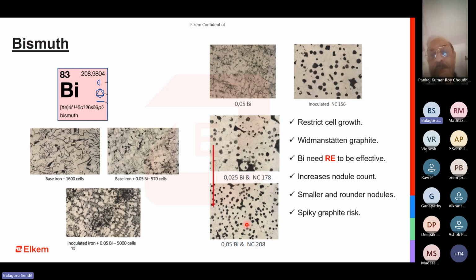The risk of what it does is that when you do not have rare earth to counter this bismuth or take advantage of the bismuth that is present, you are significantly increasing the risk of being spiky. So this is more visible in the case of gray iron. In gray iron, bismuth causes real problems because you do not have that much amount of rare earth to counter it. Whereas in ductile iron, you can escape with it.